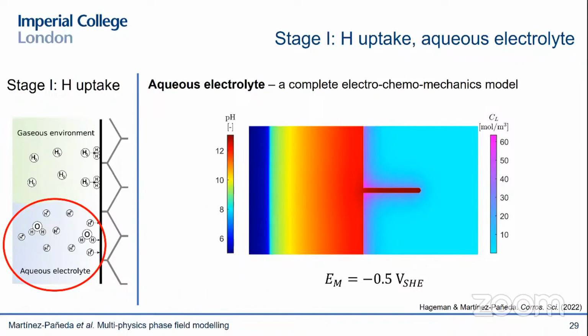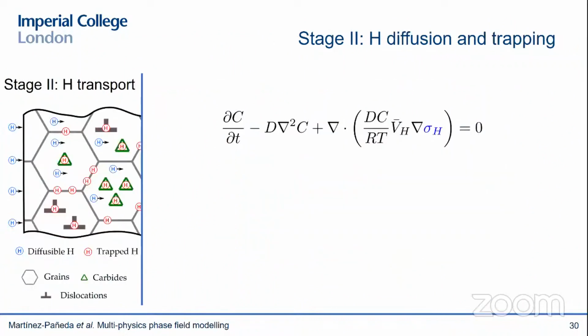And once you know how much hydrogen is coming into the metal, then you can predict the transport of hydrogen within the metal itself to predict the distribution of hydrogen within your structural component. And one simple way of doing that is by using this extended version of Fick's law, whereby hydrogen is driven by gradients of concentration and also by gradients of hydrostatic stress.